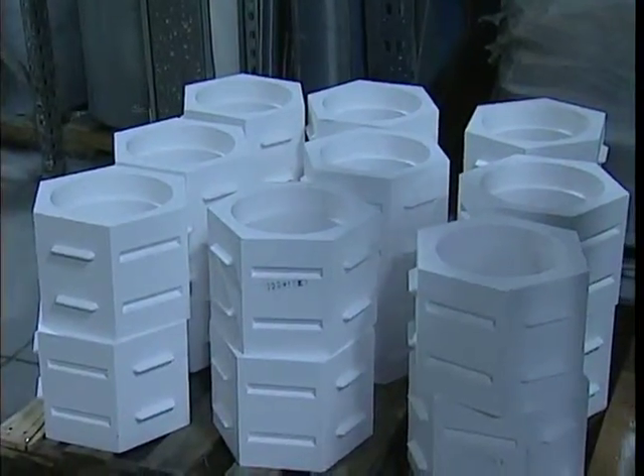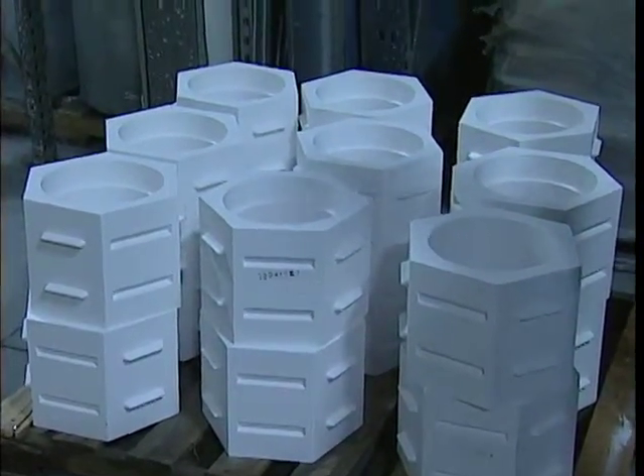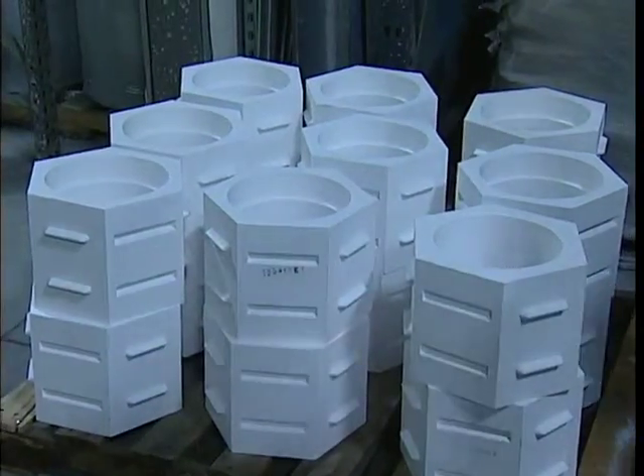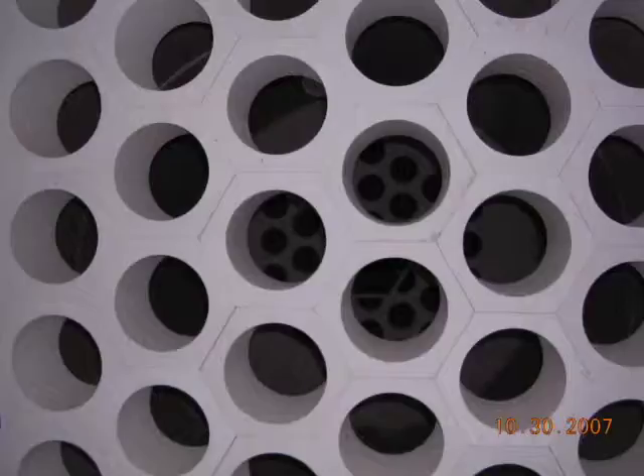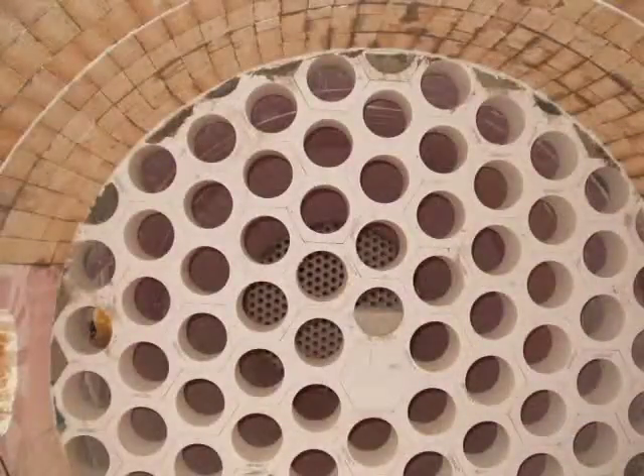look almost brand new. This is also a patented Blasch technology used to replace just simple nine-inch bricks in high-temperature sulfur recovery units. Stacks up like a honeycomb pattern. The chief advantage of this is that it's mechanically absolutely stable, where the nine-inch brick systems, although a little less expensive, ordinarily would just fall down during the service life of the product, making them useless.